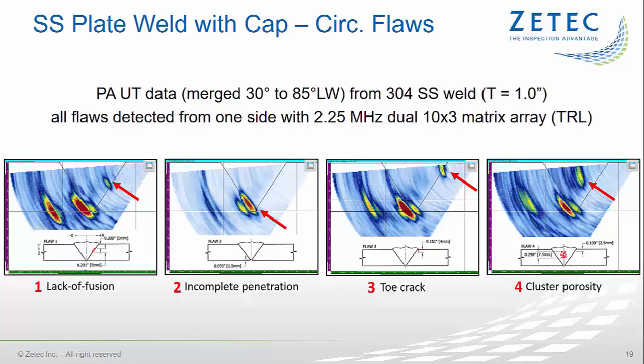In fact, the low refracted angles also provide good detection capability on ID cracks on both sides of the weld. Tip signals can be resolved for accurate sizing of small cracks from the near side of the weld. The high-angle L-wave beams provide excellent detection of a near-surface crack called toe crack without any noise from the side lobe signals. A cluster of porosity in the center of the weld material can be well detected and demonstrates the propagation capability of the longitudinal wave beams through weld material. In this case, all flaws could be detected from one side of the weld with refracted L waves generated by the standard 2.25 MHz DMA probe.